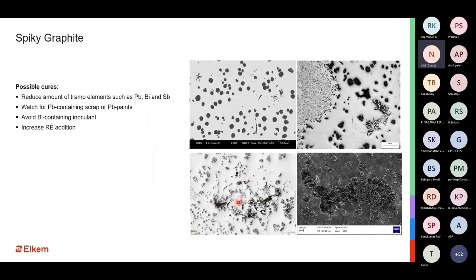How do you control it? Like I mentioned, we have to reduce the amount of tramp elements such as lead, bismuth, and antimony. Where do these come from? These come from painted scrap, especially steel scrap, which has coating paint that contains lead. We may also need to avoid bismuth containing inoculants because bismuth is an anti-nodularizer. Bismuth containing inoculants should be avoided in most cases, unless it is mandatory, so that you do not have bismuth coming into your system, thereby disturbing the nodularity.